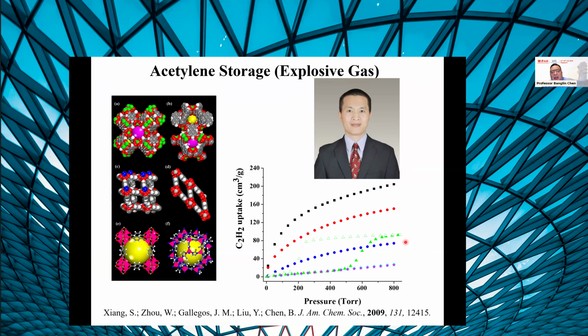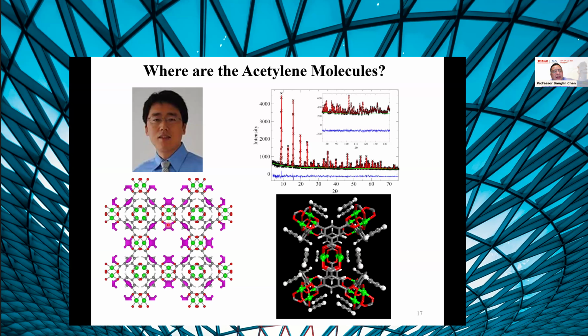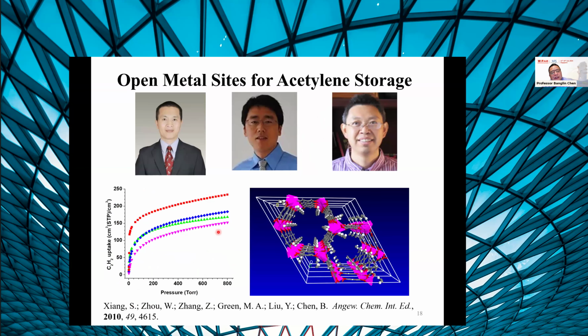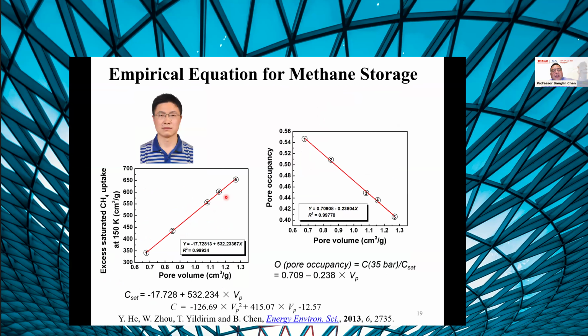And we clearly realize this open metal site is a primary binding site of the acetylene. And because of that, we further synthesize the MOF 74 series, because the MOF 74 series apparently have the highest open metal site density, and cobalt MOF 74 has the highest acetylene storage capacity. And of course, the MOF material will also be very promising for methane storage.